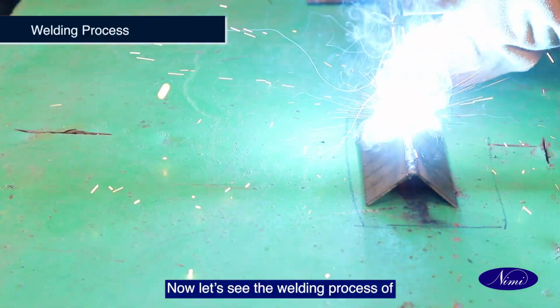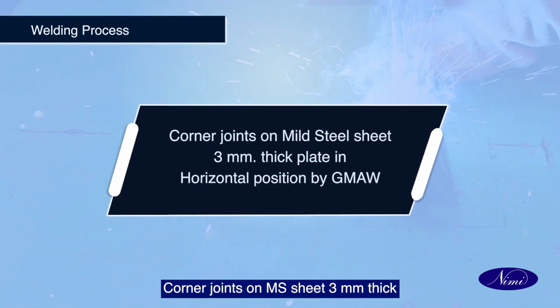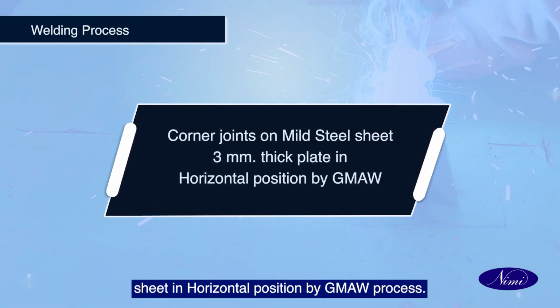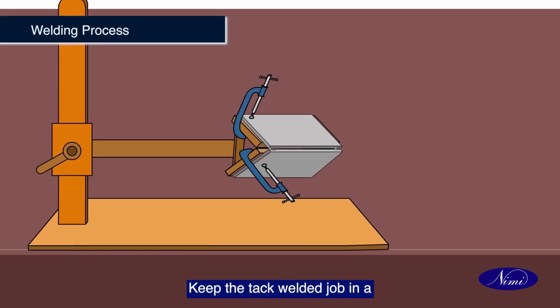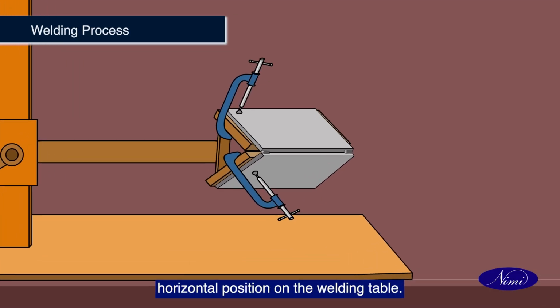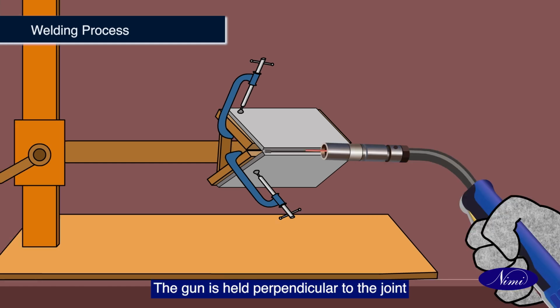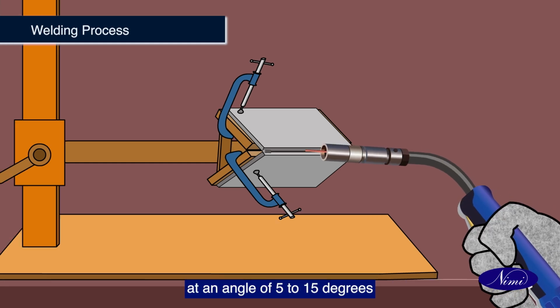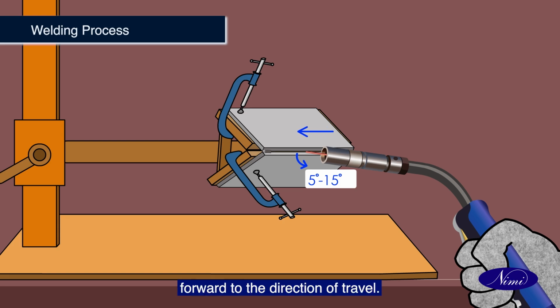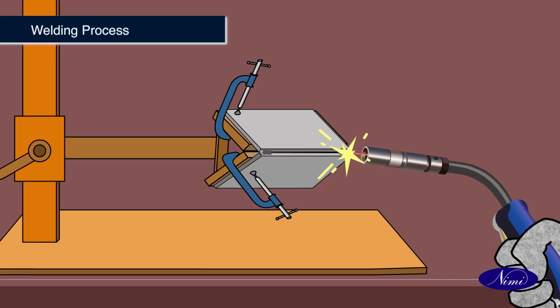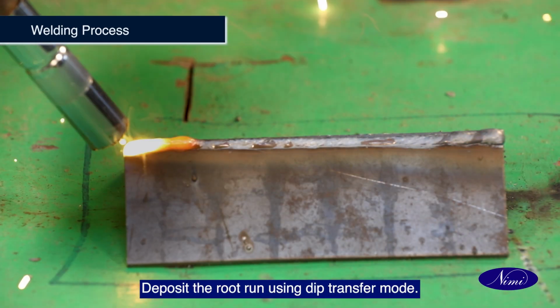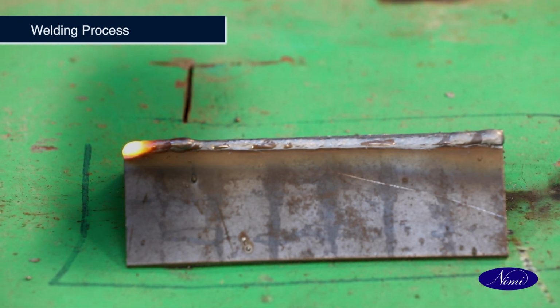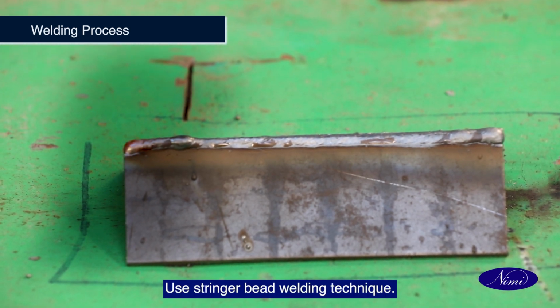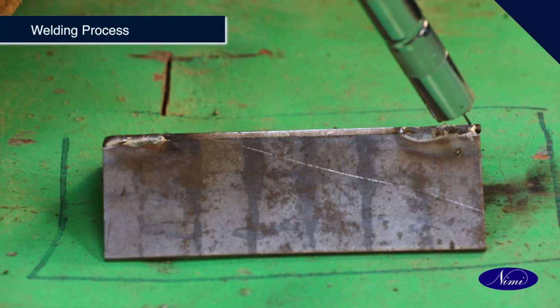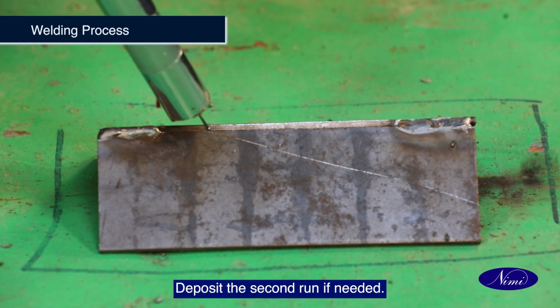Now let's see the welding process of corner joints on MS sheet 3 mm thick sheet in horizontal position by GMAW process. Keep the tack welded job in a horizontal position on the welding table. The gun is held perpendicular to the joint at an angle of 5 to 15 degrees forward to the direction of travel. Deposit the root run using dip transfer mode. Use stringer bead welding technique. Deposit the second run if needed.